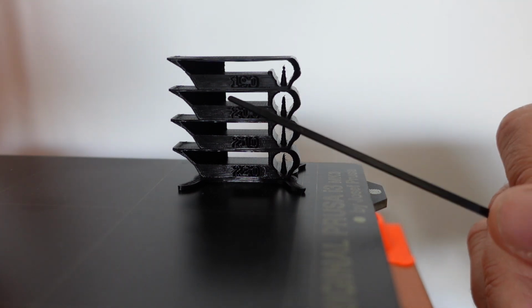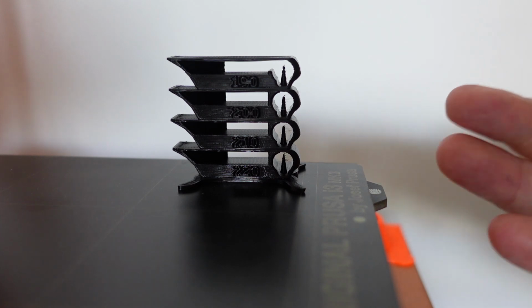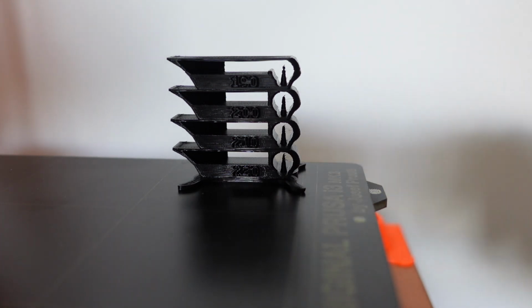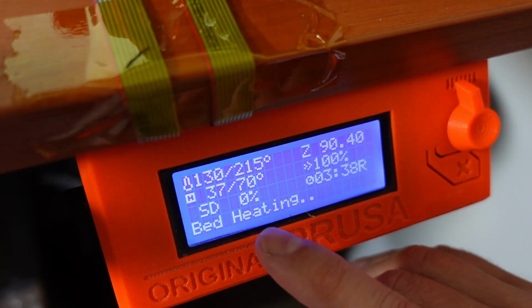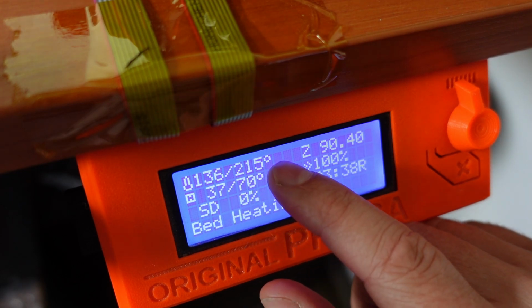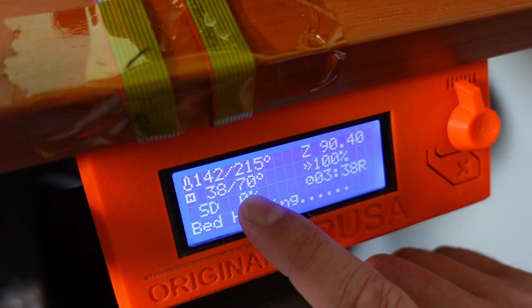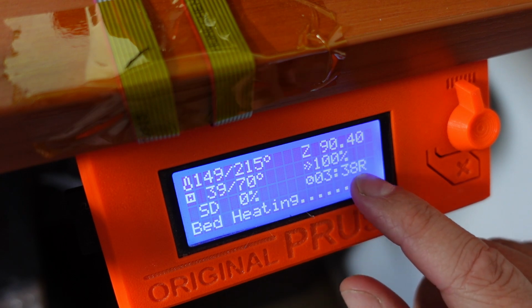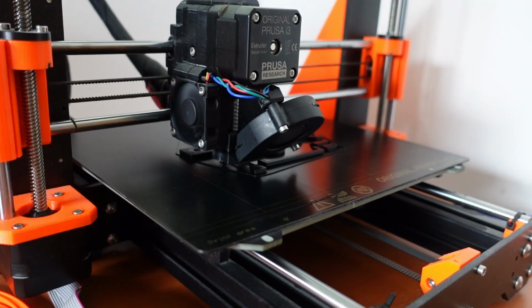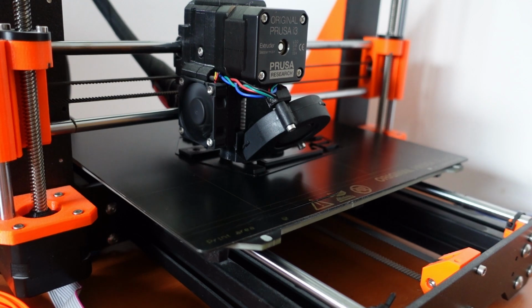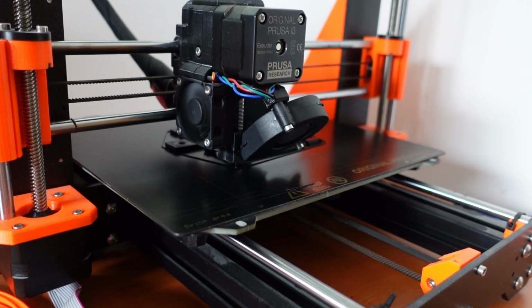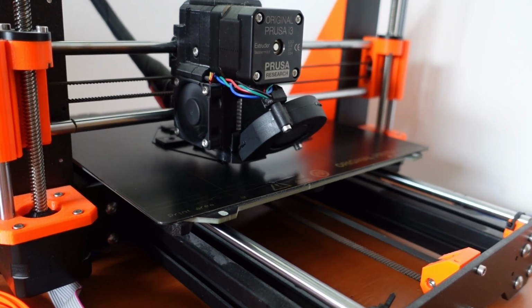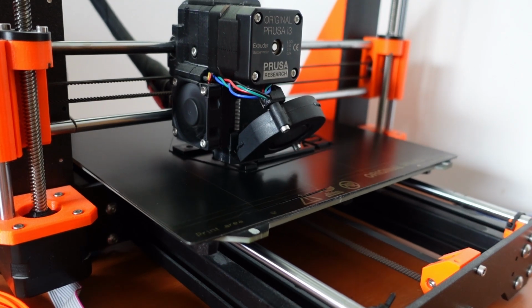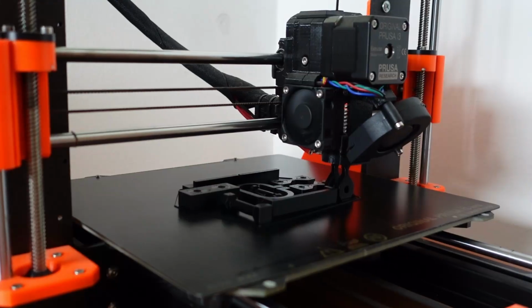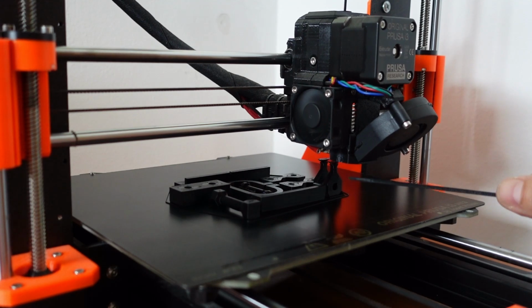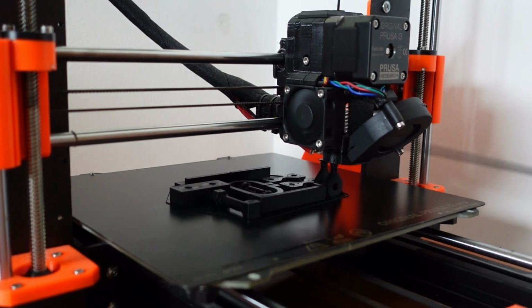Anyway, I don't recommend printing at 190 because you will get better adhesion if you print at higher temperatures. All test objects are printed at 215 degrees Celsius on the nozzle and 70 degrees Celsius on the bed, and this will be approximately 3.5 hours of printing. 2 more hours of printing, but everything looks okay so far, so it looks like it is really printable like any other regular PLA. And the last 2 objects are those printed in vertical position for the layer adhesion test.